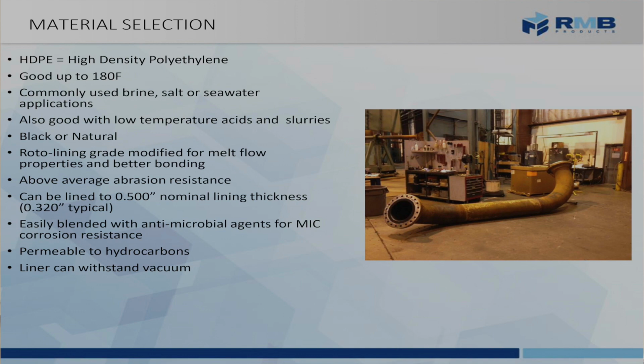This bonds very, very well. Full vacuum is provided. Typically, we're going to line this to about 320 thousandths thick. It can be lined as much as a ½ inch thick, though. And it can be provided with an anti-mic or anti-biofouling additive in case you have any problems with that. It is permeable to hydrocarbons. So there's going to be a limitation, and it's just a really good kind of everyday resin. We use it a lot for oil and gas for brine applications.